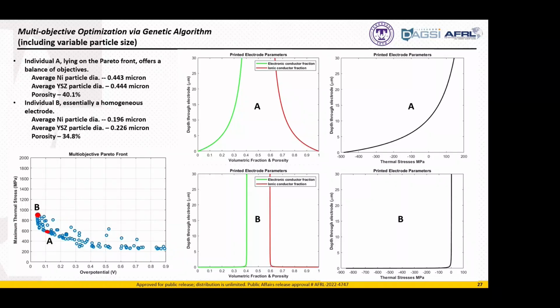And then we've also done multi-objective optimization where we allowed the solver to change the particle size. And you can see here that the results try to group the particle sizes of the two phases together. You can see that for both individual A and individual B. And then depending on the porosity and the particle size, sometimes your homogeneous cell will still have the best electrochemical performance. So this was interesting for us.